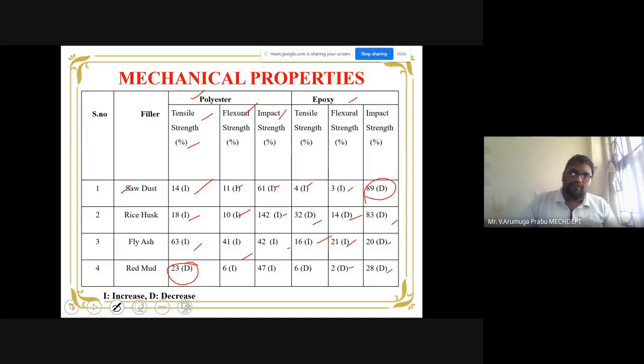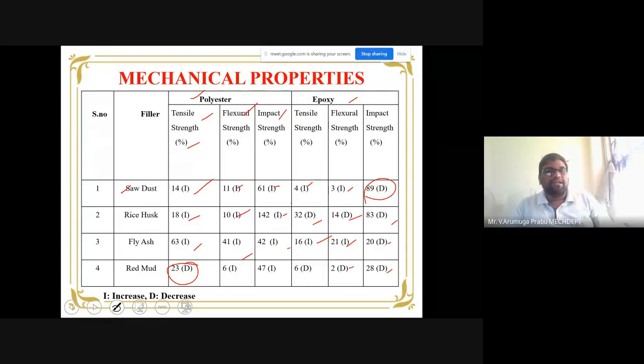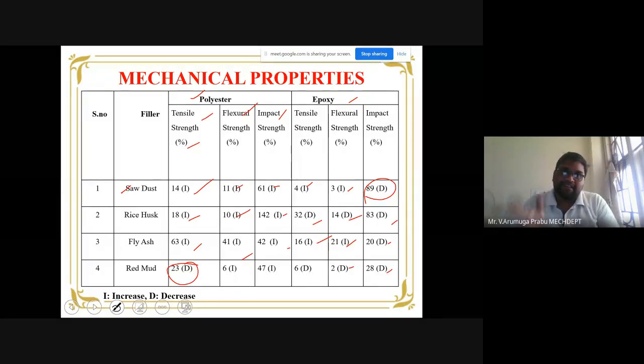Here, your filler is the reinforcement. During my earlier slide presentation, I pointed out one thing, that the main purpose of the reinforcement is to give additional strength to your matrix. So if the filler occupies one particular position, simply your matrix will remain in one area. So now your matrix does not get strengthened. That's what happens because of the non-uniform distribution, which results in the decrease that we noticed in that particular case. Other than that, we are able to notice an interesting increase in the strength. So now these results I am showing purely for your filler and matrix. That is, the filler is the reinforcement, and the matrix is your polyester and epoxy matrix.